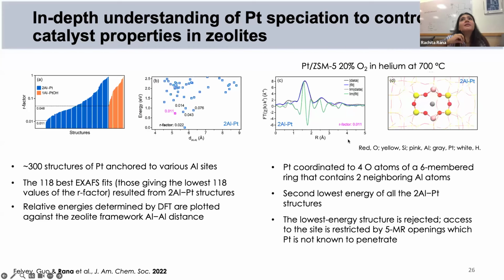And so it's really going by what your EXAFS fit is telling you, and at the same time combining the relative energy of your structures in the database to identify what could be the potential site that you're looking at in the system. And then this material was used for oxidative studies and other things in future. But I just wanted to highlight that it's not just a specific system that you have to use. As long as you can rely on DFT and other characterization tools such as infrared spectroscopy, you can really answer questions using QuantEXAFS for a well-defined material.